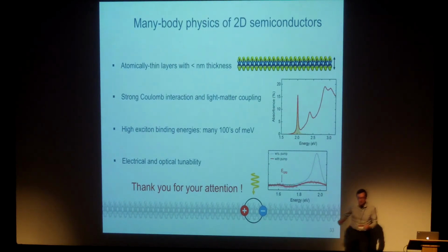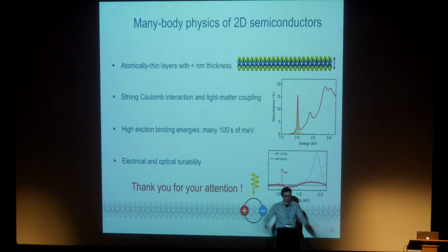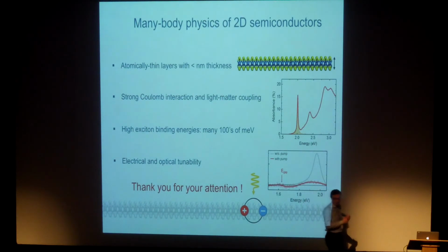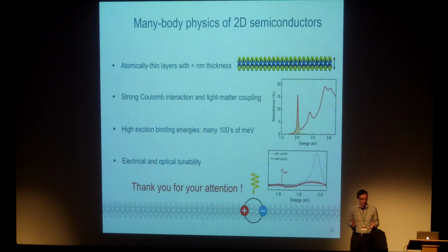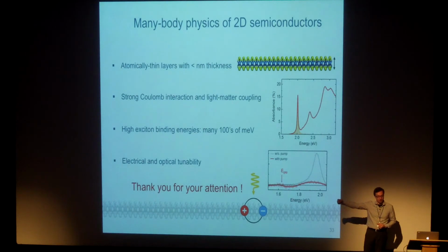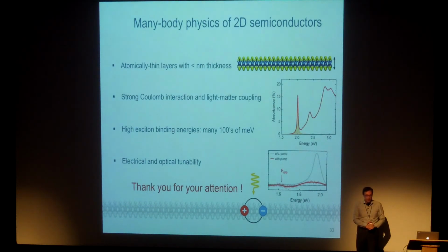Because the exciton basically, as soon as it starts to move, cannot emit light, because its momentum is too high. But for the trion, this rule doesn't apply. It can always satisfy the momentum relation by giving it to the extra electron. What we can think about with respect to trions is that we now have an opportunity to move excitons around. For example, talking about light-matter coupling, Bose-Einstein condensates and polariton physics, we'll have an opportunity to have a charged polariton, or a stable one. So we'll basically have a particle which is half exciton, half electron, half photon, so to speak.